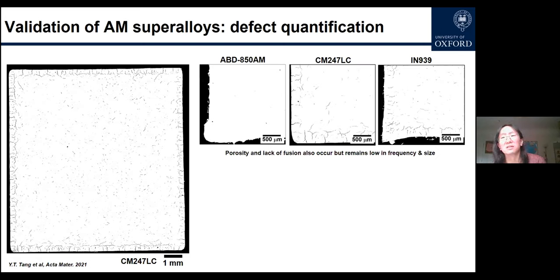If we try them at different compositions, we can see that the newly designed alloy composition becomes a lot easier and more forgiving to this process, without too much defects. Particularly, these are not very critical. But just to be frank, the alloys we have designed here have a much lower gamma prime fraction. That means this is not going to be the most heat resistant material compared to the other materials which have cracks. However, that is a good start.